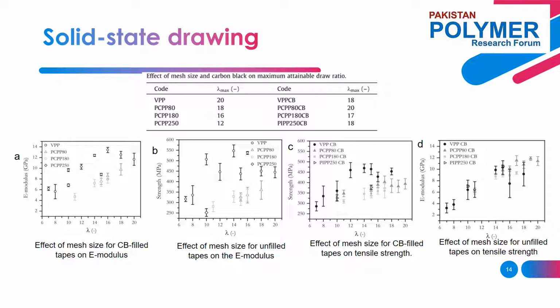The effect of melt filter mesh size on the mechanical properties is shown in figure A, B, C and D. For both unfilled and carbon black filled material, the elastic modulus and tensile strength are not directly affected by the size of the mesh, but the tapes can be drawn further, yielding drawn tapes with enhanced properties.